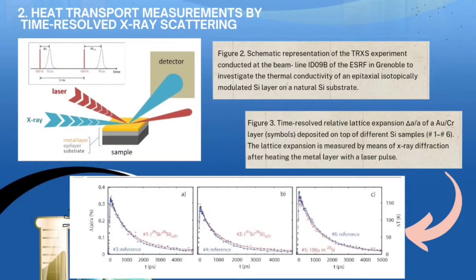The cooling of the metal layer after pulsed laser heating was followed by measuring the Au lattice constant with X-ray pulses as a function of time. The inset of figure 2 shows two consecutive laser pulses with the variable time delay between laser and X-ray pulse and their corresponding pulse duration. In practice, integration over the scattering response of about 2000 consecutive pulses at fixed delay was performed to increase the signal to noise ratio. Figure 3 illustrates the time-resolved relative lattice expansion of the Au layers on top of samples 1, 2 and 5 in comparison.